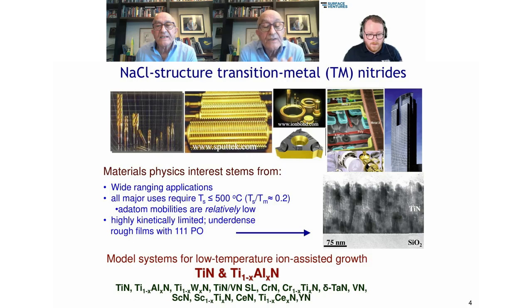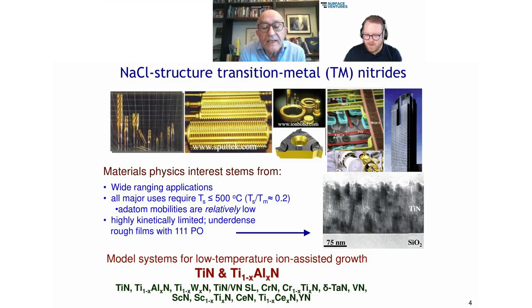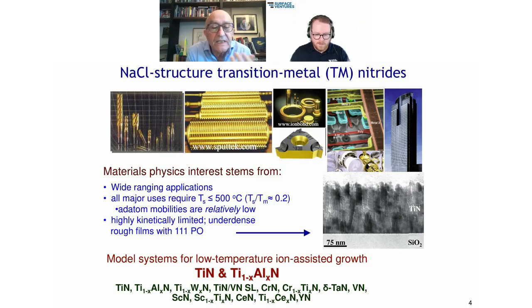So as model systems for ion-assisted growth, the materials we use are sodium chloride structure cubic transition metal nitrides, primarily titanium nitride and titanium aluminum nitride, because of their wide use in practice and diverse application. These are refractory materials, with the melting point of titanium nitride above 3,000 degrees Celsius.